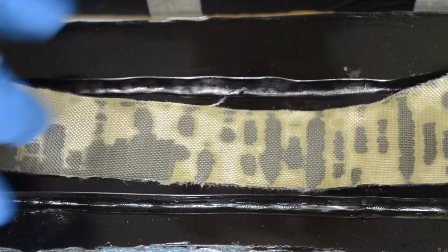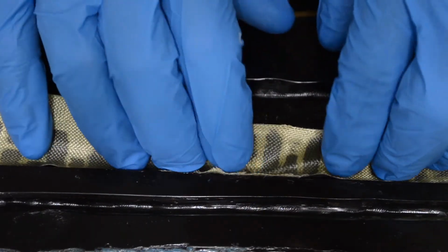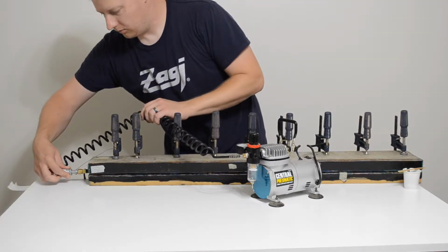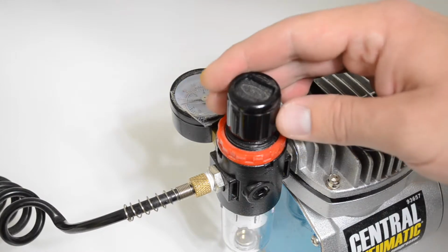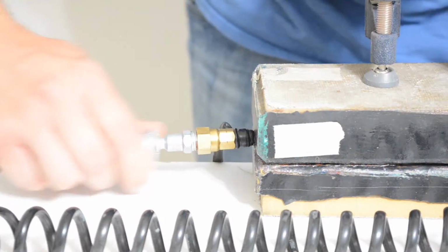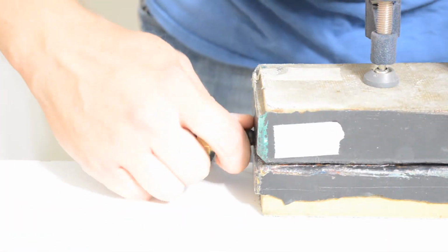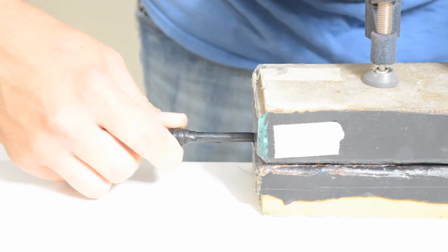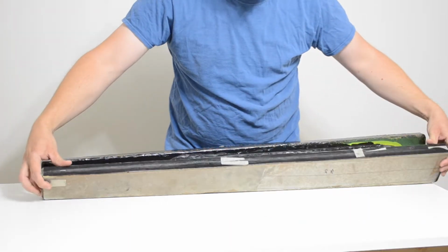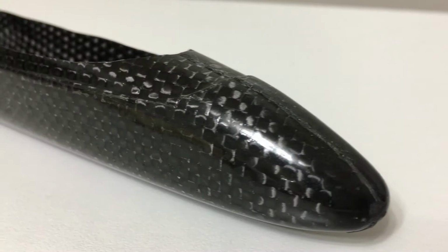This is the technique that I use to make the fuselages for my gliders. And I ramp the pressure up to 60 psi, 4 times higher than I can get with just a vacuum bag. And it's noticeably easier to get a really shiny surface finish. And what's more, it compacts the plies even more, so I have a really good bond from one ply to another, and you get a really strong part.